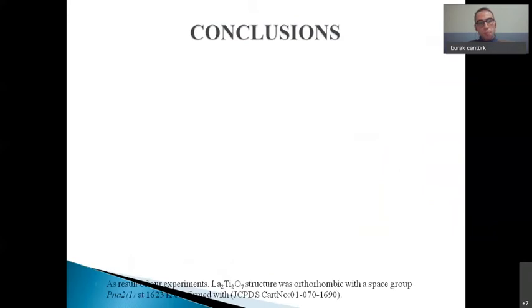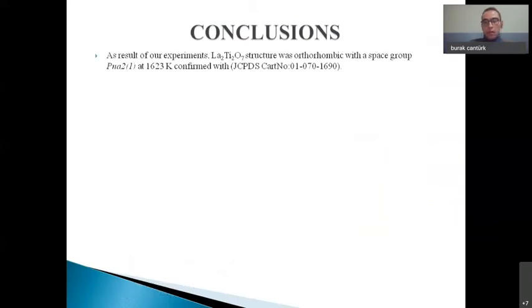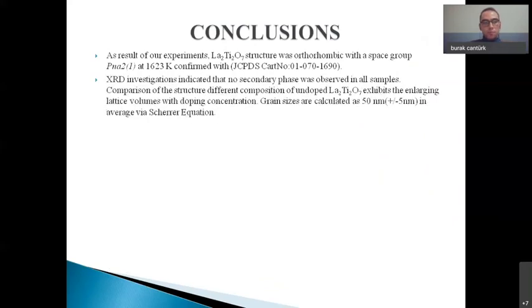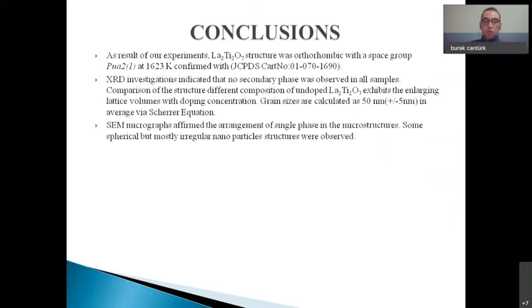To sum up, as a result of our experiment, the lanthanum titanate structure was orthorhombic, and the XRD investigations indicated that there was no second phase observed in the samples, and also the grain sizes are calculated as 50 nanometers on average via the Scherrer equation. The SEM micrographs affirmed the single phase in the microstructure. Mostly irregular shapes were observed.